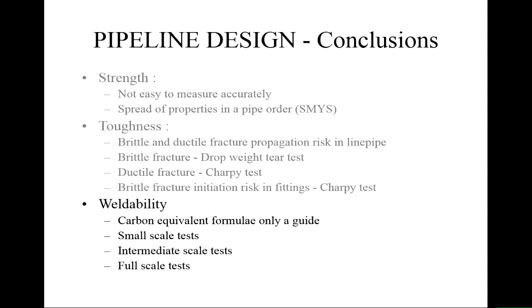Small-scale tests in the lab can prove a procedure for trial, and then it has to be tried on intermediate scale tests on pipe pups and things like that to make sure that it's a practical test that the welders can do reliably and give you good results. And finally, you have to do full-scale tests, because without that you can't guarantee that the welding procedures are going to be suitable, and you therefore need to qualify every step of the welding procedure, not just the depositing of metal, but the handling of the pipes and things once that has been done.